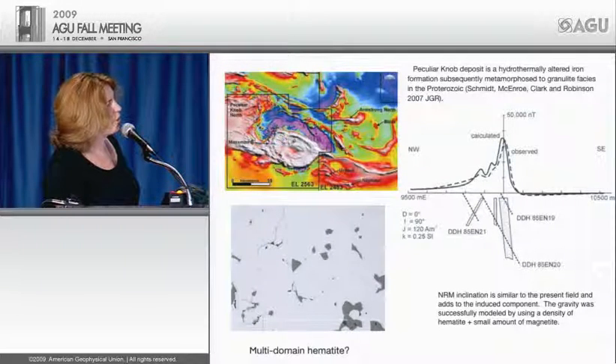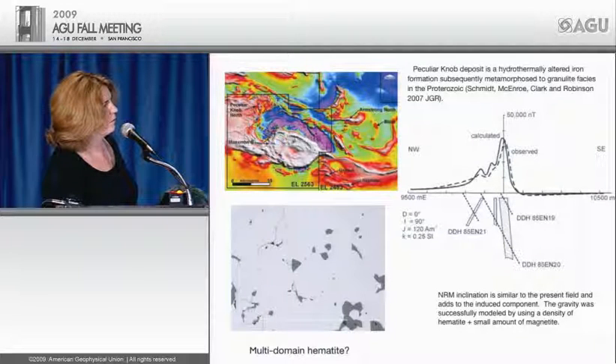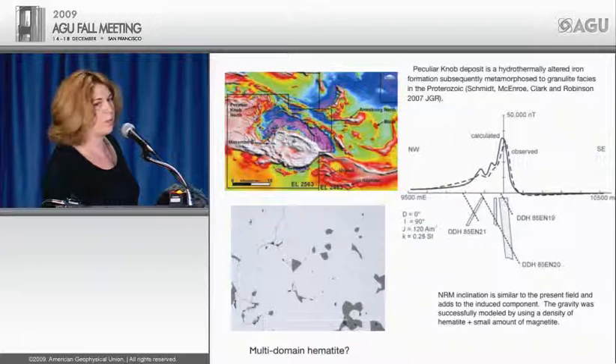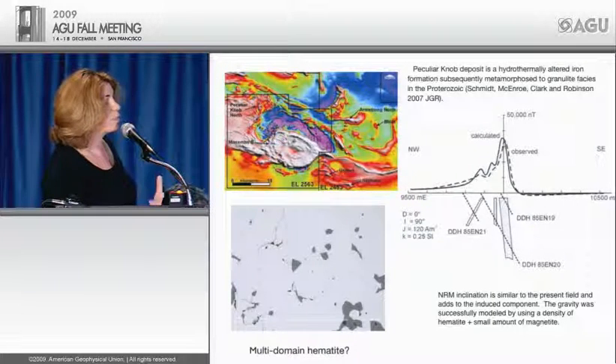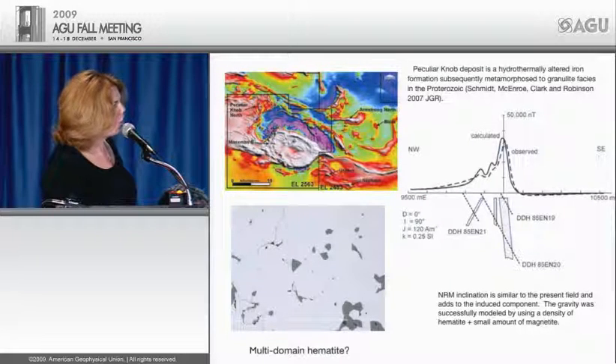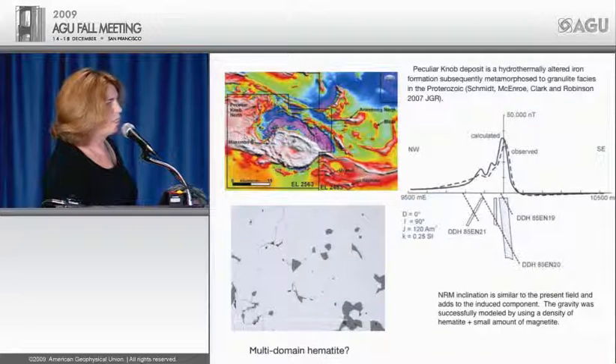But I want to just point out here what it took to model this anomaly. The anomaly needed 120 amps per meter to model. It's an enormous remanence that's being carried. Of course, this is an ore deposit. And here we have very large millimeter-sized grains of hematite, and the hematite themselves never gave pure hematite analyses. And this was really quite frustrating.